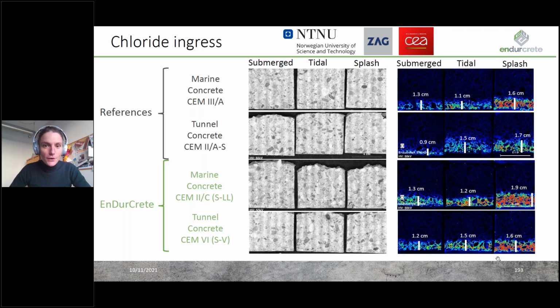If we then compare the reference concretes, the 2 top rows, to the EnDurCrete concretes, there are actually no large differences. That's also what Irina presented when she showed the results from the exposure site. Our EnDurCrete concretes are more environmentally friendly concretes, and they are performing similar to the references. So that's a very good thing. They're more environmentally friendly, but they're as resistant as the references to chloride ingress. So this is a sneak peek of results.